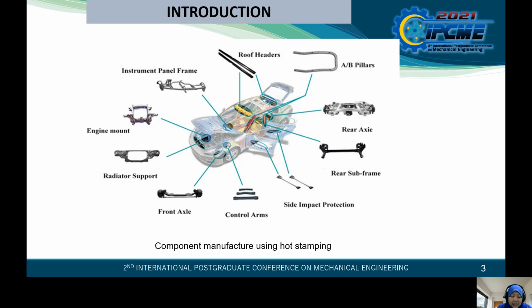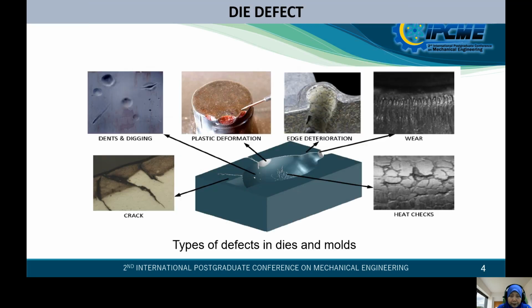Recently, Proton Malaysia use hot press forming technique to improve safety element when car crash. Die is one part in hot stamping component. When in use, die are exposed to surface condition, regular wear, impact, corrosion, thermal cycling, and high stress that cause deterioration to the die. Figure show type of defect in die and mold. The defects are dent and digging, plastic deformation, deterioration, wear, crack, and heat check.